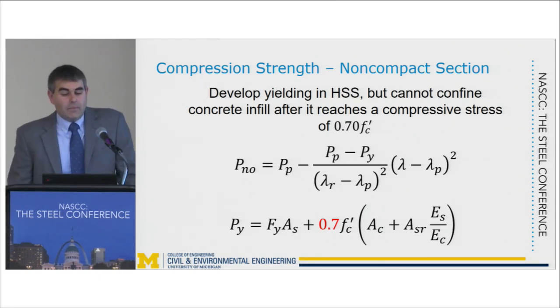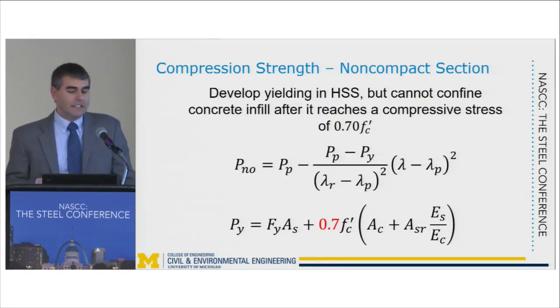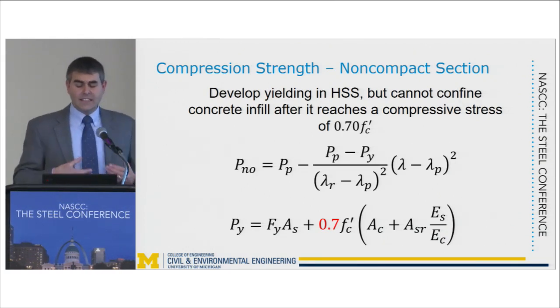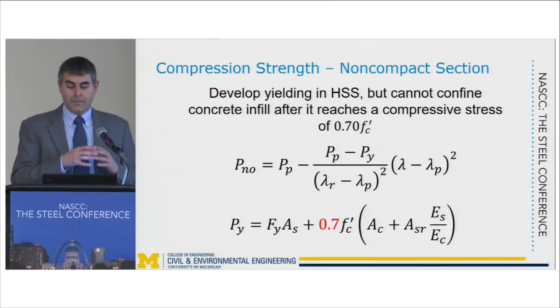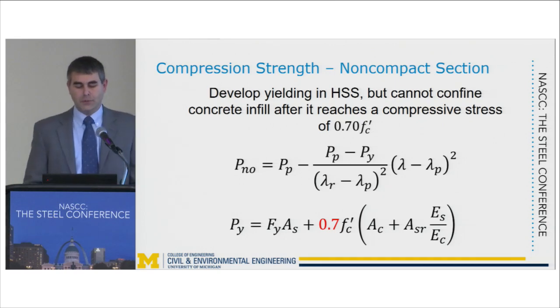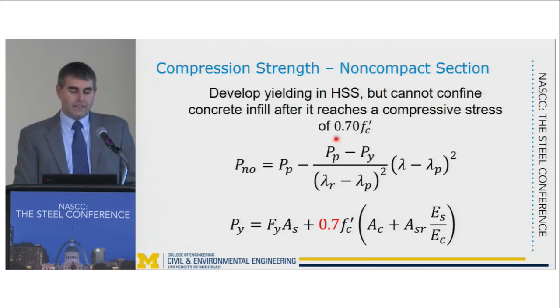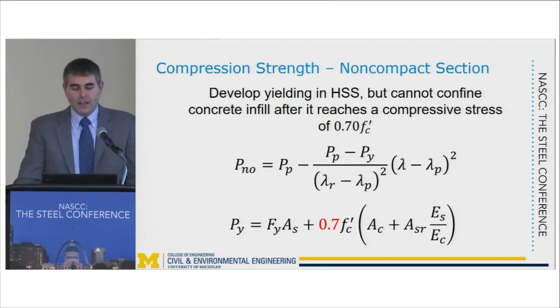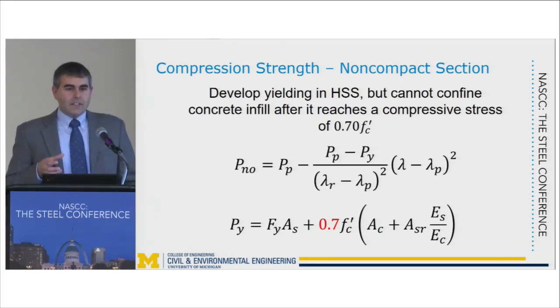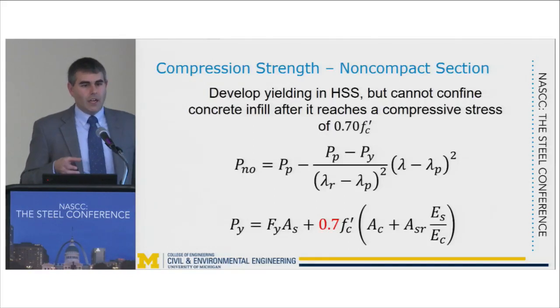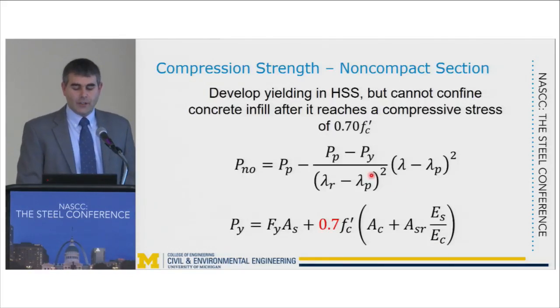Now, if we look at a non-compact section, for these sections under axial compression, we're going to assume that we develop yielding in the HSS, but we can't confine the concrete infill as a result of the inelasticity that the concrete undergoes and the volumetric dilation, which tends to push on the wall of the HSS tube. And as a result, we limit the compressive stress in the concrete to 0.7 F prime C. And what we're going to do here, in order to calculate the strength for a non-compact section, is essentially take a quadratic